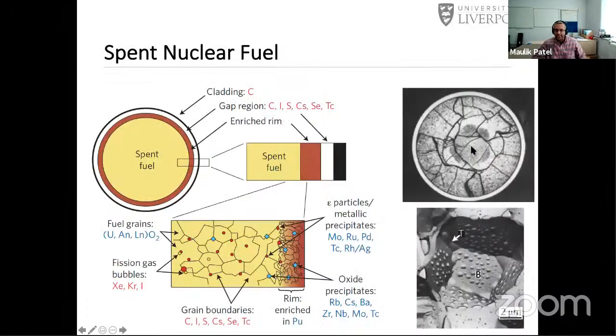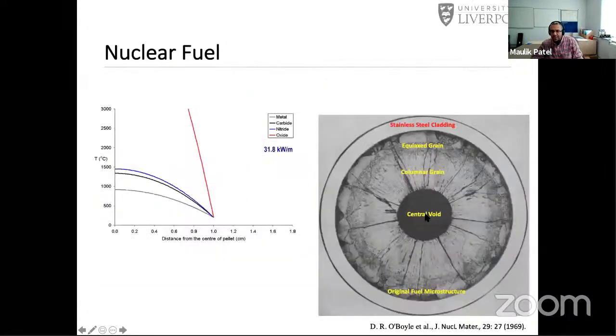So this one doesn't have a hole in it, but you would think that these are simple pellets that are made by pelletizing, but that actually is a whole mechanical engineering side of making these pellets. These pellets actually have a sort of a dimple in the middle, and they're engineered so that they can take heat stresses, and stresses can then be distributed in the pellet itself. The one that you saw earlier was a fuel that was used in Magnox fuel, which intentionally had a void space in order to reduce these microstructural changes, in order to take this temperature gradient into consideration.